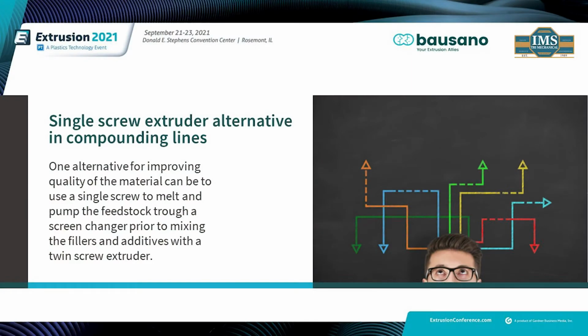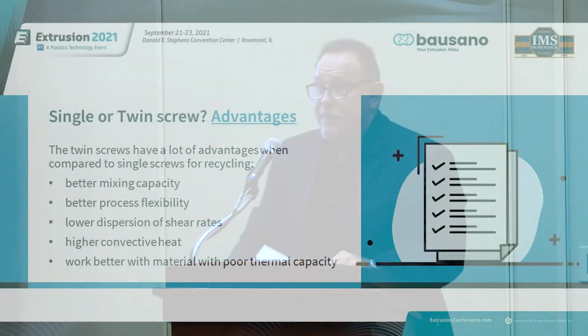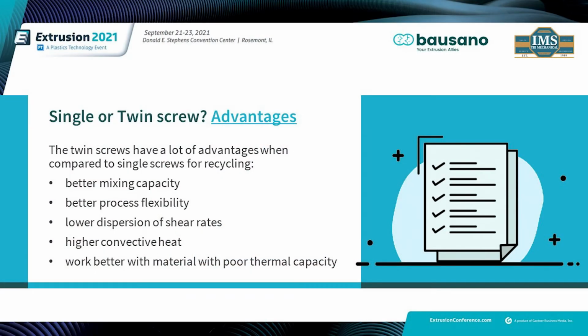Some processes require an ultra high quality in the end product. In this case, where low contamination is paramount, some manufacturers use a single screw in conjunction with a twin screw. A single screw extruder is used to melt and pump the feedstock through a screen changer prior to the fillers and additives with the twin screw extruder. This process allows the twins to mix with less energy used, saving on the need for more stabilizer. In fact, twins make better pellets.